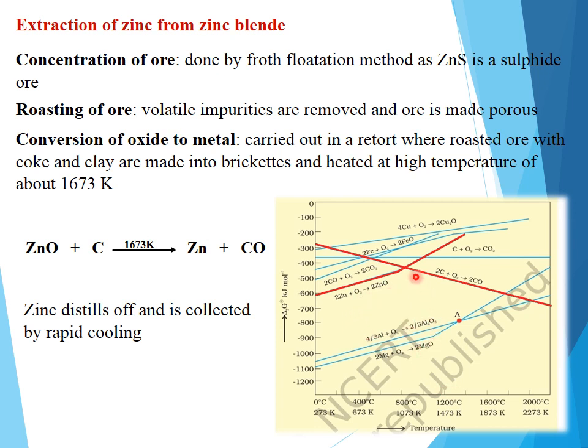When you talk about higher temperatures, here you can find this graph, carbon monoxide from carbon. This graph is intersecting at this particular temperature. After that temperature, the carbon monoxide from carbon graph is coming down and the zinc graph is moving up. Even this graph where carbon dioxide is formed from carbon is also lying below the zinc graph. So we can conclude that at higher temperatures, around 1600 to 1700 Kelvin, coke can be used as a reducing agent, since in the Ellingham diagram the carbon monoxide from carbon and carbon dioxide from carbon graphs lie below the zinc oxide graph.